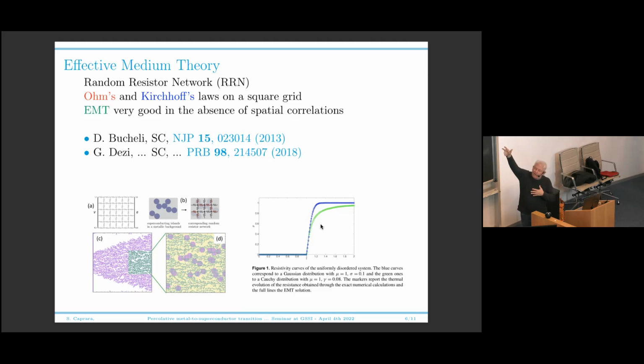So we were playing with some fractal structure. You don't really need it to be fractal, because in the end you are taking a finite sample of it. So it will never be a scale invariant fractal. It will be a system where you are producing some filaments. The green filaments here are produced by the so-called diffusion limited aggregation. This is just some machinery that you can invent to produce some filaments. And then you decide that your superconducting cluster only exists on those filaments, okay? So now your superconducting cluster is no longer homogeneously distributed in your system, but only exists on these filaments.